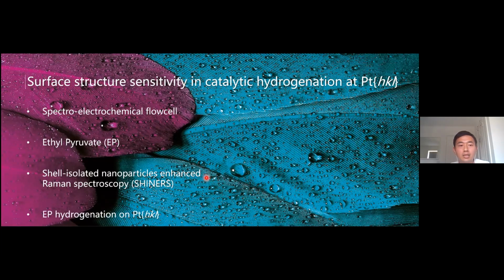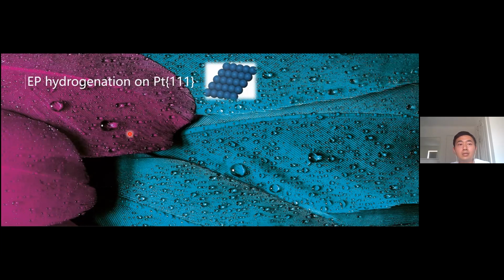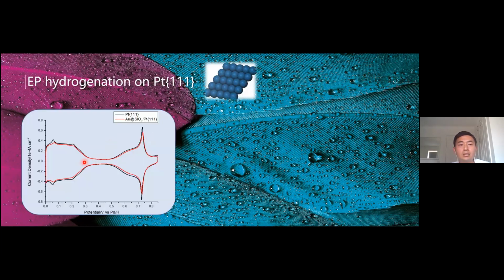Then again, I studied the EP hydrogenation on different platinum single crystal electrodes. First, let's look at the platinum 111 surface. This cyclic voltammogram shows that after depositing the nanoparticles on it, it retains its features, which proves that this nanoparticle is inert.